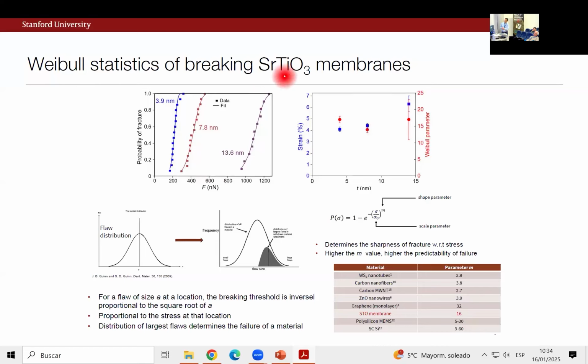Whereas as it stretches out, this is saying some of my membranes break early and some break at a much higher force level, right? And so the higher this m value, the higher the predictability of failure. So whatever underlying statistics and distribution of defects we have, this characterizes their contribution to fracture. What's interesting is, if I plot the results for strontium titanate membranes in the context of things from MEMS to nanotubes and graphene, it's actually got quite a decent shape parameter in terms of the predictability of failure.